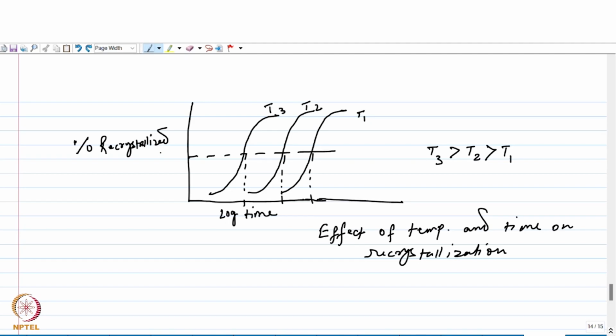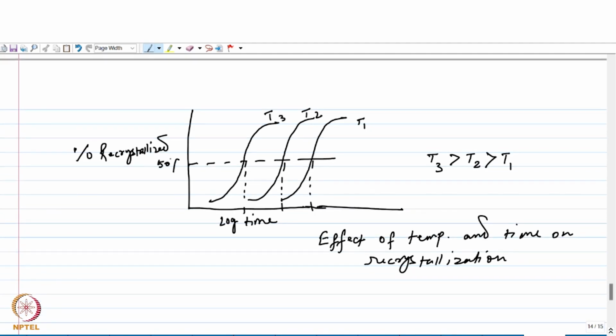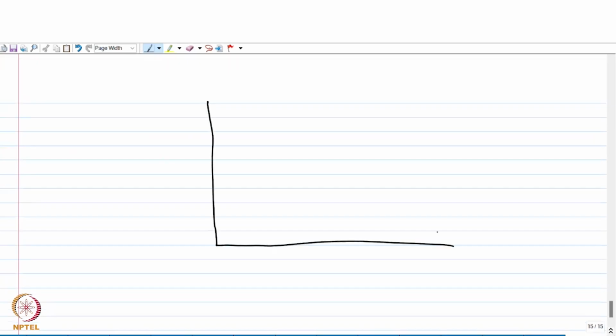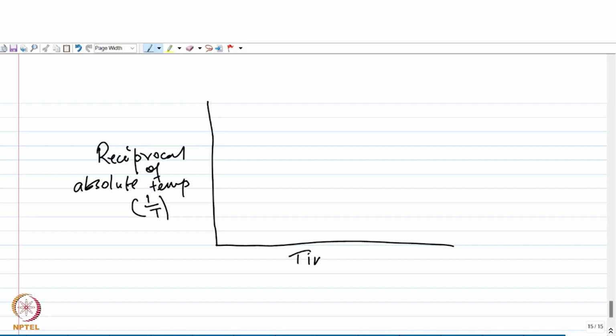If we consider this fraction as 50%, the fraction corresponding to this horizontal line, we will get the time required for recrystallization of half of the structure. Okay, so if we call that time interval as tau and plot it against the reciprocal of the temperature, we will get a plot like this, where the y-axis is the reciprocal of the absolute temperature, and the x-axis is the time for half recrystallization.